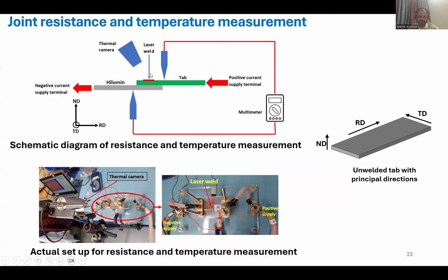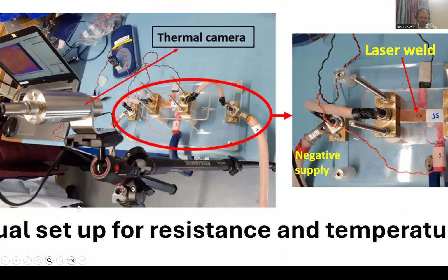At the same time I am capturing using the thermal camera. The thermal camera is focusing on the weld area only, and it is capturing the temperature range at the weld because the current is going to pass continuously. I am going to pass this current for 3 minutes or 5 minutes, capturing the resistance and the temperature at the same time, the real-time temperature and real-time resistance. So this is the arrangement.